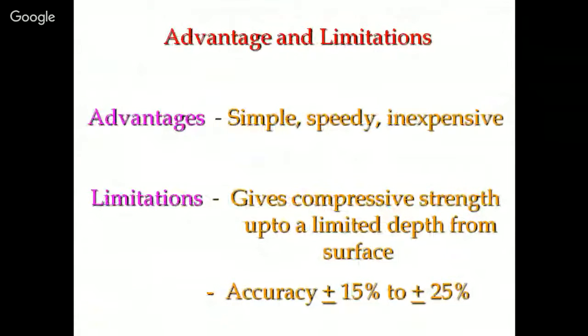So the advantages of the method: simple, speedy, inexpensive. Limitations: it gives compressive strength only up to a limited depth from the surface, and accuracy is plus minus 15% to plus minus 25%. But if you compare it with the results of cubes, the code says that plus minus 15% is acceptable, so it falls within that range.